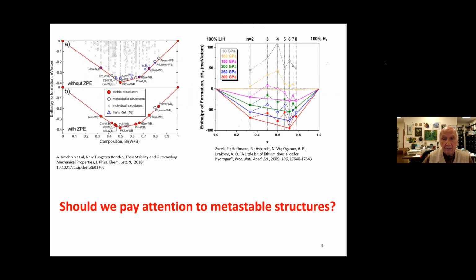Now, let's see, I'm having trouble advancing this. Here we go. Here are two typical convex hulls of this type. At left, from Oganov's work, it's on tungsten borides at 1 atmosphere, and at right from one of the first papers we did, in which we used one of these diagrams, in which we looked at lithium hydrogen compounds and found that at high pressure there were also stable points for LiH2 and for LiH6. And you see also lots of metastable minima. So these were local minima that were stable to small distortions, but were thermodynamically not stable with respect to decomposition to the elements plus one of the compounds on the convex hull.